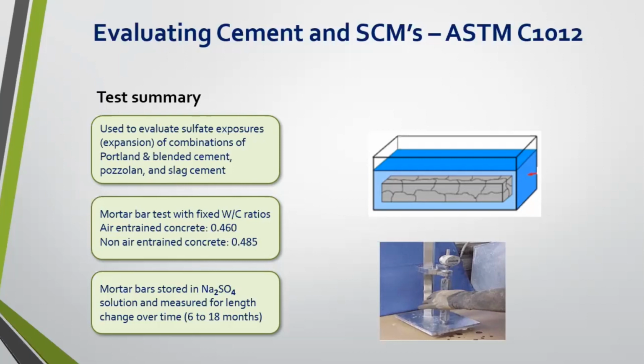So this is a mortar bar test, and it's got fixed water cement ratios. So if it's an air entrained mix, we're going to use 0.46. For a non-air entrained concrete, we'd use a 0.485. And these mortar bars are stored in a sodium sulfate solution, and they're measured for length change over time. The earliest test being at 6 months, going all the way out to a year and a half. And I like the picture that's shown up there. You can see the cracking starting to take place in the animation there as it's soaked in that sulfate solution.